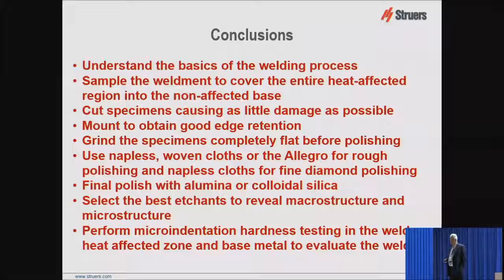And you want to cut samples, and this is true for all metallography, causing as little damage as possible, because this is where the major amount of damage occurs, and you've got to get rid of that. And if you're working with titanium, for example, the removal rate when you're grinding and polishing titanium is much slower than any steel or copper or aluminum or anything else. All the refractory metals have that same issue.